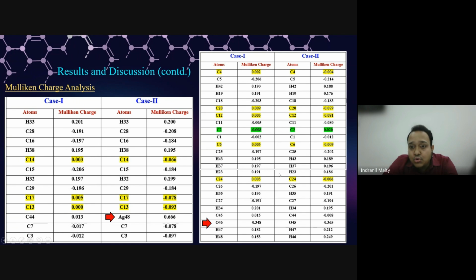And in the yellow marked region, if you compare the left side with the right side, you can see that in the case of C20 and C12, the values are positive, but in case 2, the same two values are negative, whereas in the case of the green one, the initial value for pristine graphene is negative, but here it is positive. So all the charges are modified.